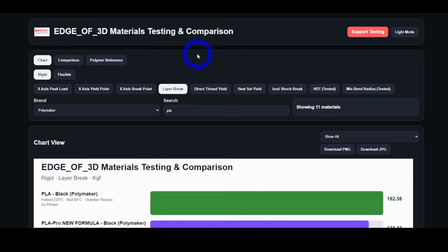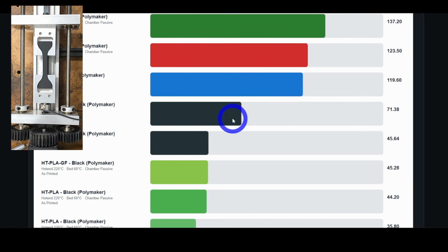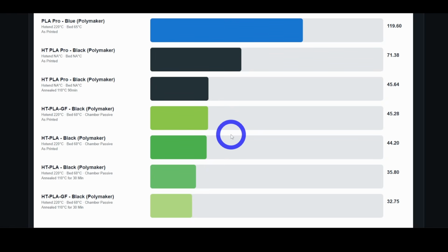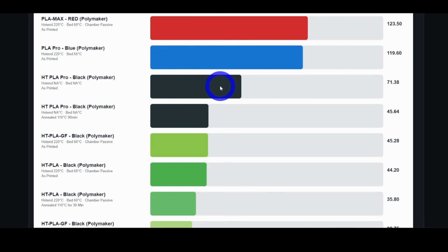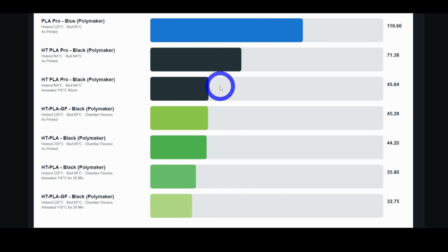Layer adhesion. Their claim here is a tougher PLA with better layer adhesion. Let's see. The original HT-PLA formula: annealed, 35.8 kilograms layer adhesion; as printed, 44.2. Here's the HT-PLA Pro: annealed, 45.64, so 10 kilograms more force than the standard HT-PLA. And 71.38 kilograms layer adhesion on the non-annealed HT-PLA Pro versus 44.2. So pretty significant before it's annealed, and still significant after it's annealed.